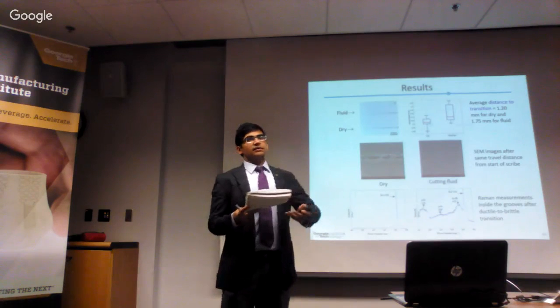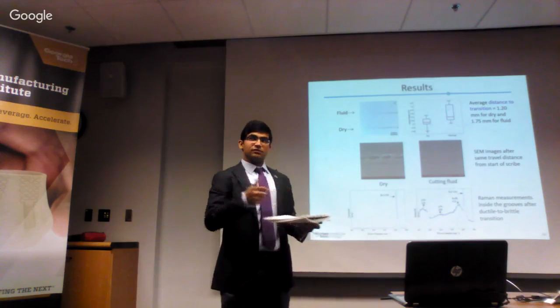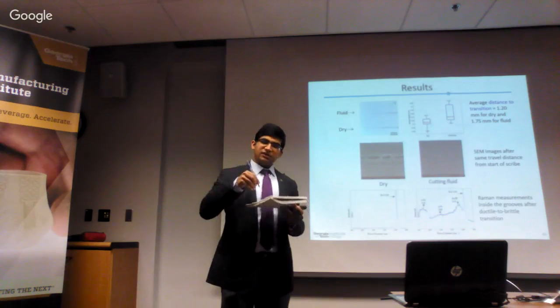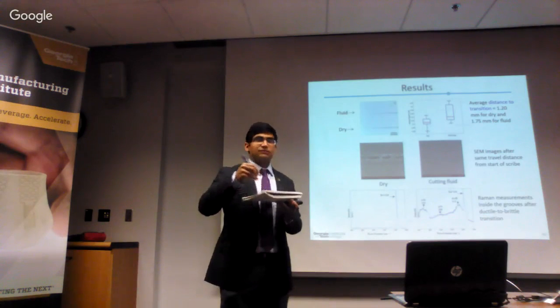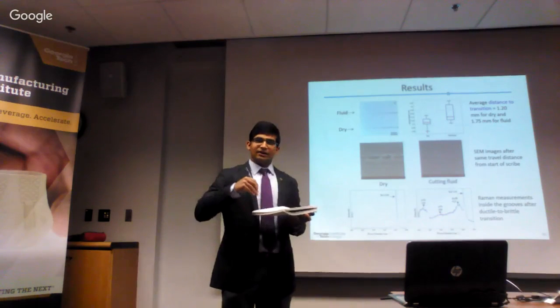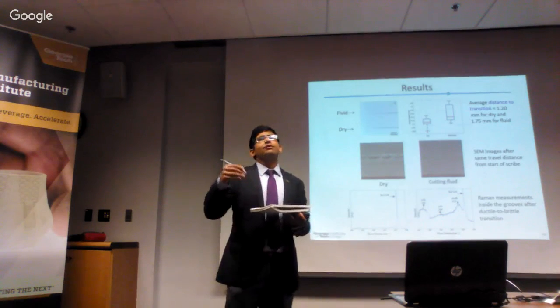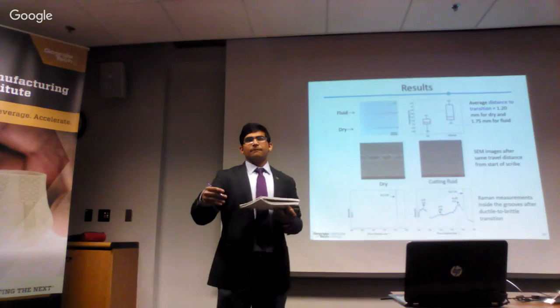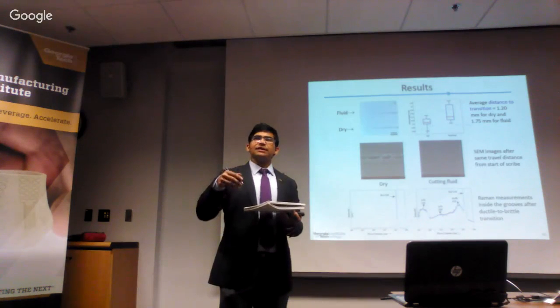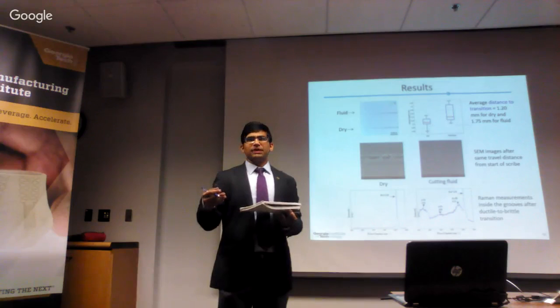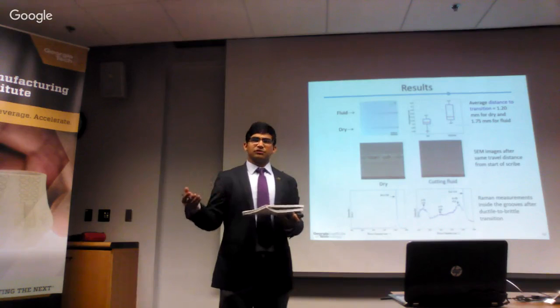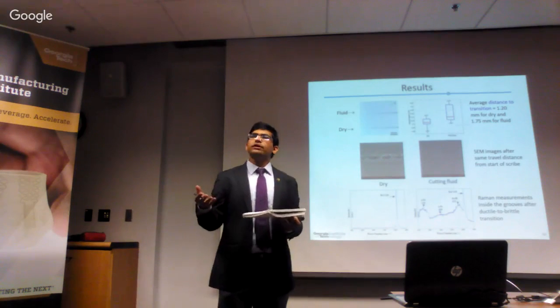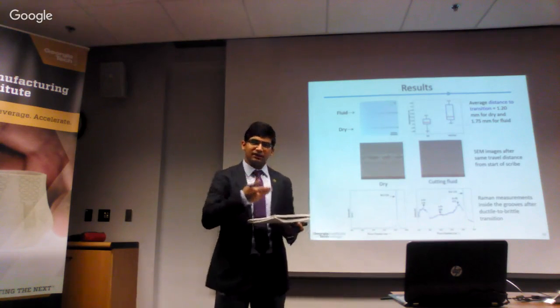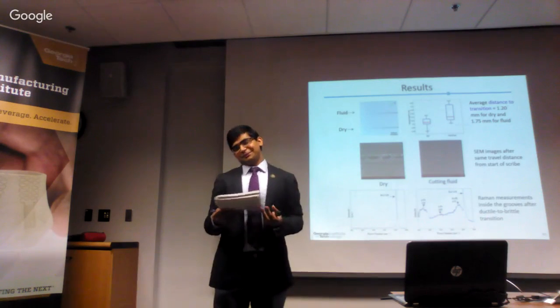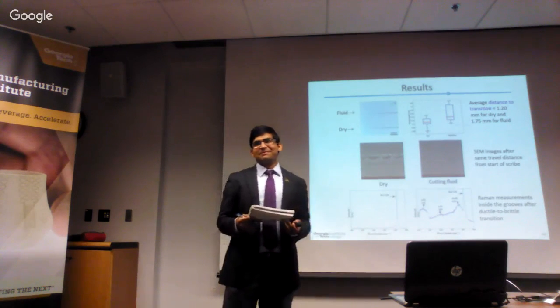Now, the question you're asking is whether the fluid film is indeed changing the stresses. I feel that in this configuration, with the indenter getting in touch with silicon and then creating the scribe, it is in very close contact between the diamond and silicon, and the fluid film thickness may not be enough to change the stress, or for some stress to be taken by the fluid. That hypothesis may not apply in this case. That's still your hypothesis. Because you haven't tested it.